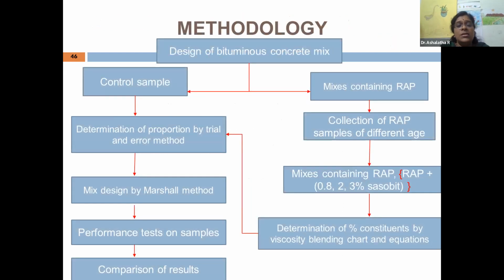So this was the methodology we used, similar to the other one which we had discussed for the design of the RAP mix. But here, we have two samples, with material collected from two locations. For each location, we conducted the test with 0.8, 2, and 3% Sasobit, and then determined which is the best one. Then a performance test was conducted on that, the results were compared, and it was also compared with the virgin mix.